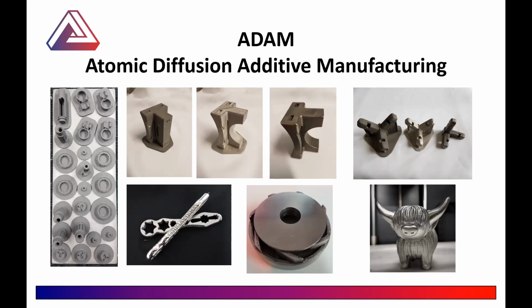What I maybe should have said there, when we're printing the part, we are printing the part with the material. And we've also got a material that we print in between, which really separates the support material and the actual part. And once that goes into the sinter, that actually turns into a powder, and allows the part to be separated.